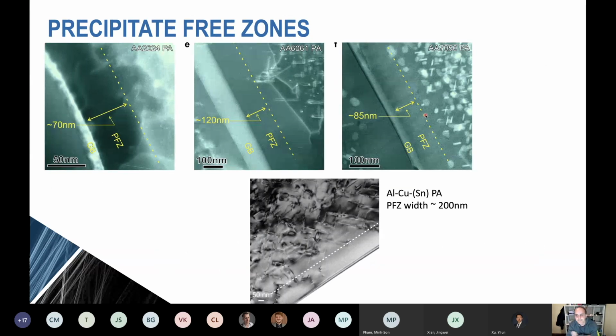And to give you an example, here are some precipitate-free zones in the sorts of alloys that we've been using. So you can see up here, this is 2024, an aluminium copper magnesium alloy that's been peak aged, 6061 in the peak age state and 7050, and all of these materials contain precipitate-free zones anywhere from 70 to 120 nanometers in size. And so that's a reasonable size precipitate-free zone. Here's an aluminium copper example, and the precipitate-free zone can be about 200 nanometers in size. And so this is very important, because what you have here is a comparatively weak zone next to a hard grain interior. And that has some big effects on the mechanical response, particularly on the damage properties.